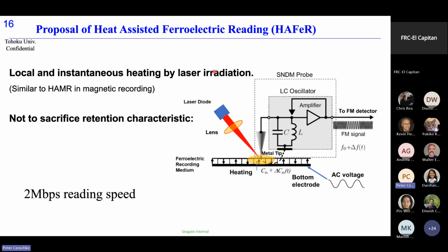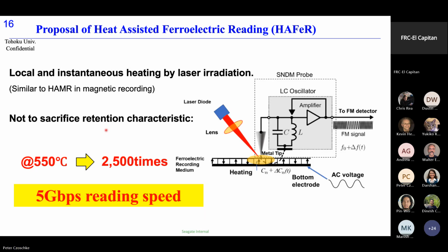And so last time, as I told you, we proposed a new reading method, a heat-assisted reading. We call this technique HAFeR. This is a local instantaneous heating by laser irradiation. The mechanism is very similar to the HAMR in magnetic recording. But due to the short heating time, this method does not sacrifice the retention characteristics. If we assume the temperature of the material at 550 degrees Celsius, 2,500 times larger non-linear dielectric constant is expected. So in principle, Gbps order reading may be possible.